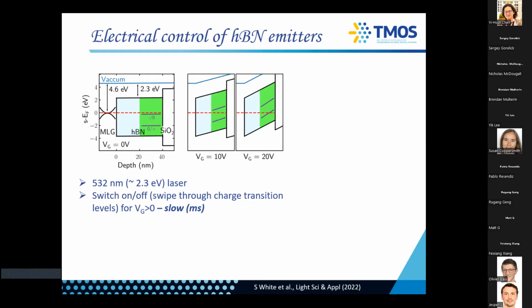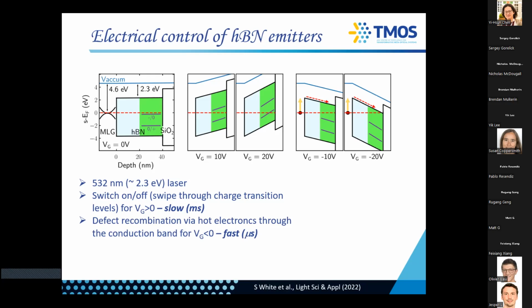If you look at charge switching of the NV center, NV minus and NV0 are both optically active, but they don't have to be. In the case of hBN, one of them is active and one of them is not. This is why when you increase the bias, some of the emitters go off. As a function of depth, where the emitters are located within this layer, your slope will be different, and that is why some emitters turn on at 5 volts and some at 15 volts. And with negative bias, you would have a different effect.